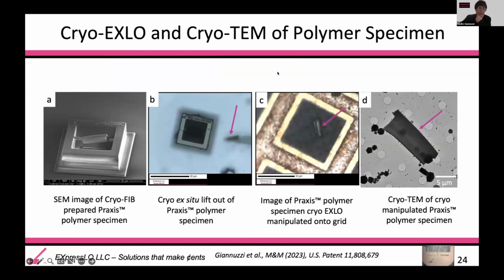So our first attempt at trying this was with those polymer Praxis samples. So this is an SEM image of the finished FIB specimen. Then it was transferred. This is the micromanipulation. You can see the specimen at the end of the probe. This is placement of the specimen onto a C-flat grid, and then we transitioned it into a cryo TEM. We can see a little bit of contamination here during the transfer that fell onto the grid itself.